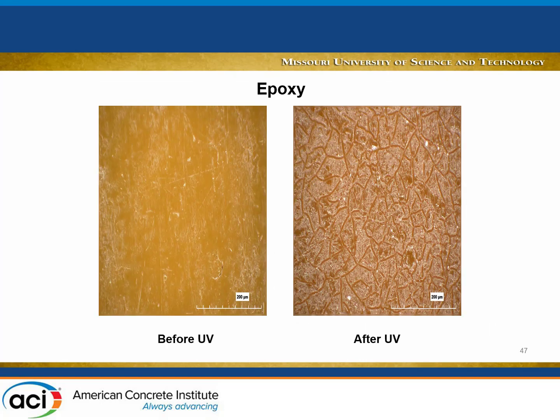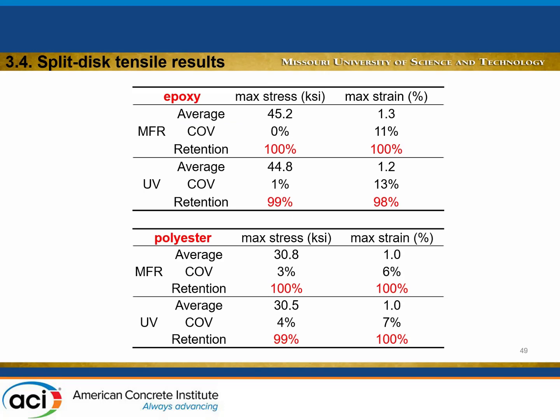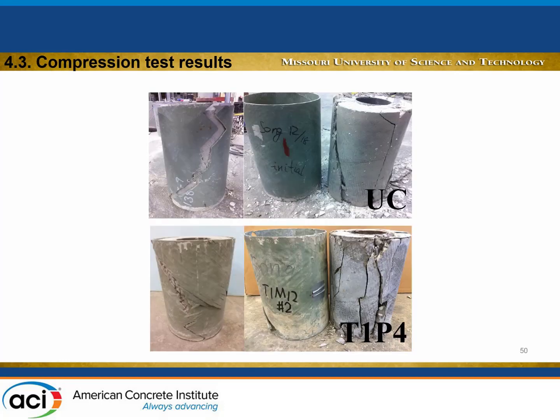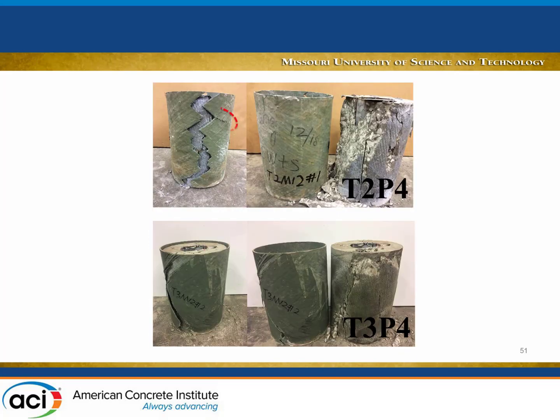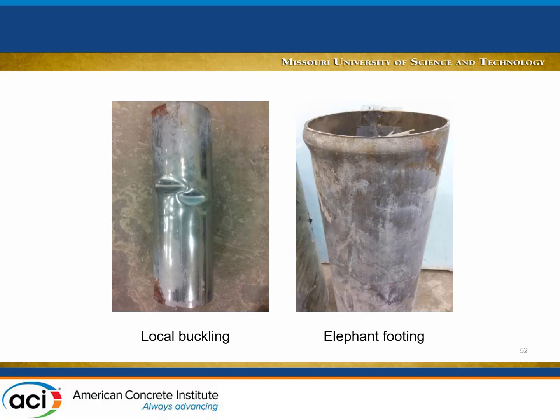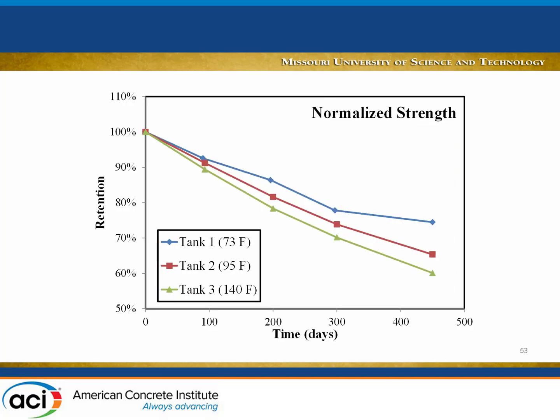This is how the specimens look after the UV. You see some micro cracks, if you like, on the surface here, but they are superficial, because when we did the ring test, we didn't see much difference in terms of strength and strain. When we tested the ring after the UV, you lose 2% for the epoxy, and for the polyester, we almost lose nothing. Then these are the specimens that were placed in the tanks. There is some buckling of the steel inside the tubes, and this is the normalized strength. Whenever we have a high temperature for a long duration, you lose about 40% of your axial capacity. The reduction here decreases as we go.